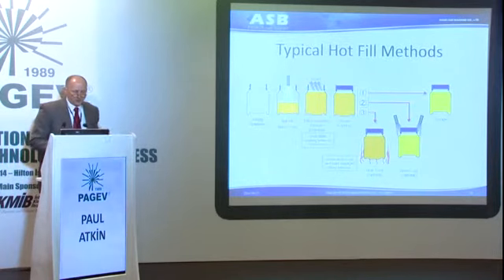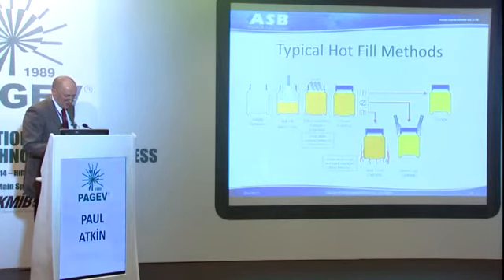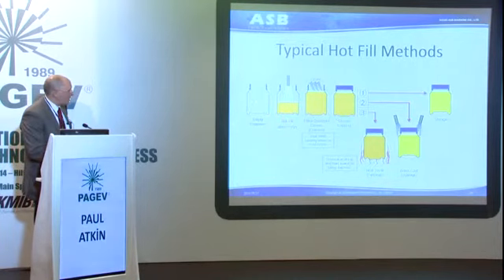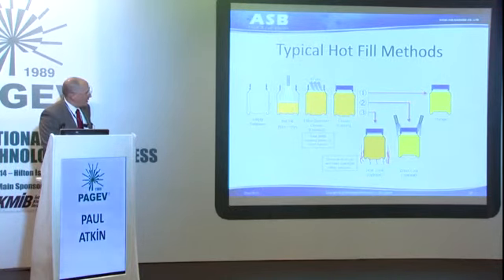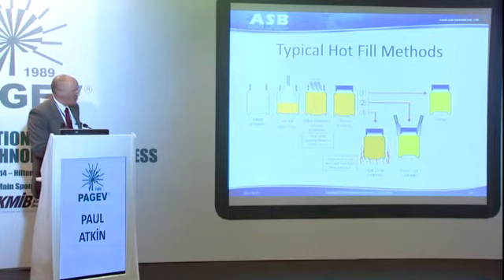This is just some typical methods which are used. Just try and find the laser. Starting here on the left, we have the empty container which we rinsed. It will be hot filled. It may or may not be flashed with steam. This provides extra sterilization, but also rapid cooling of the steam helps to create a vacuum at the capping phase, which is very critical. What happens to it after that depends on the nature of the product, pH values, viscosities, etc. It may be naturally cooled, it may be force cooled, or it may go through additional pasteurization.